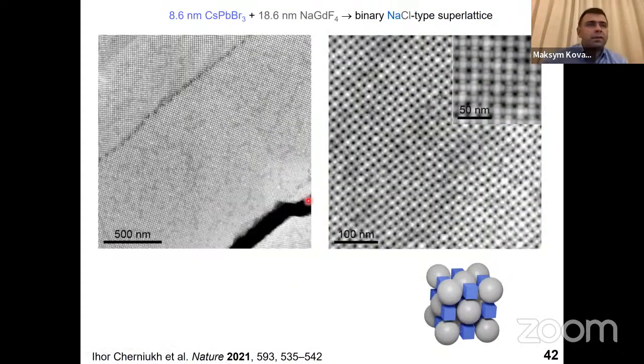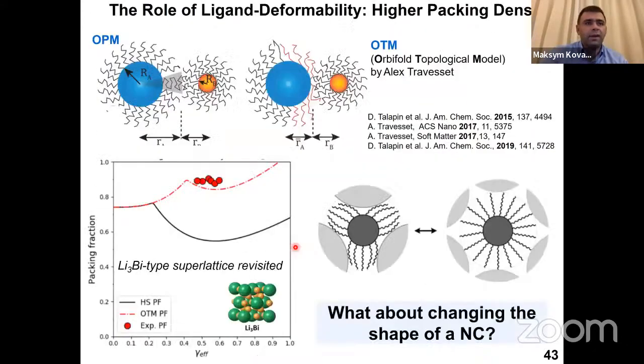Okay, so yes, it's a dielectric sphere, sodium gadolinium fluoride, and you do get again the same type of crystal structure. Now, we have observed much more interesting structures, but before you will understand why they form, let me also bring your attention to the fact that your ligand shell is not only deformable, but it can deform in a very specific manner. That was observed years ago and was invoked to explain the stability of some of the binary all-sphere assemblies, which would otherwise be hard to explain.